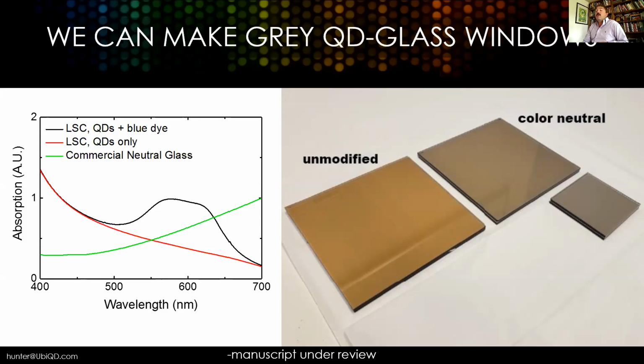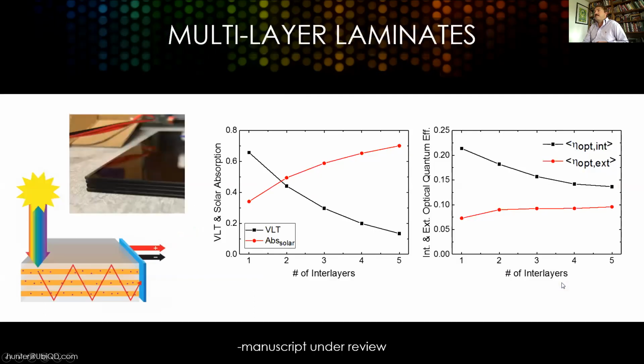One way that you can address this with the brown material is by adding an absorber on the red side. So basically a dye that looks blue, or something that makes a blue color, would be a red absorber. And by adding that to a brown, you basically balance out the color. You can see here, going from unmodified to increasingly adding the blue dye, you can get to a blue color fairly easily. This does compromise performance a bit, but you'll have to stay tuned for the manuscript, which is under review now, to get the full story on that.